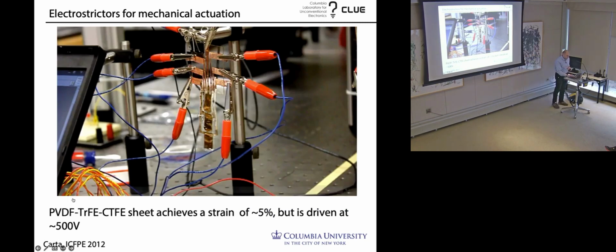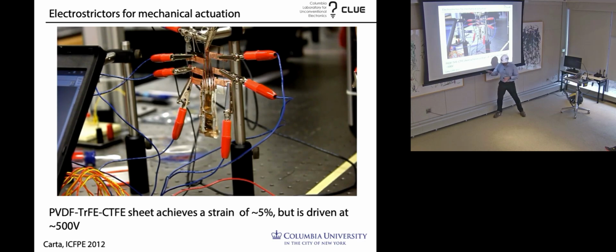So I mentioned a lot about sensors, but where can we go with actuators? This is a material that I'm really obsessed with. This is a polymer material, which is related to PVDF, but it's a terpolymer, and it has a very high dielectric constant, close to 50. So it's a really great electrostrictor. And when you apply a voltage, you can get almost 5% strain.